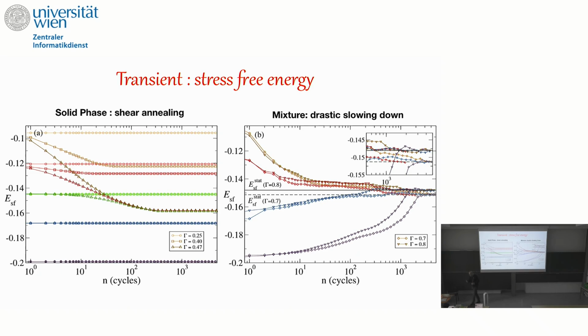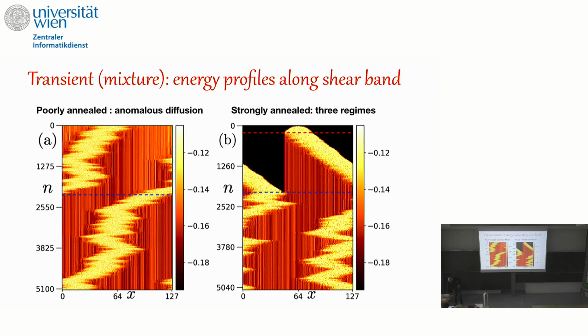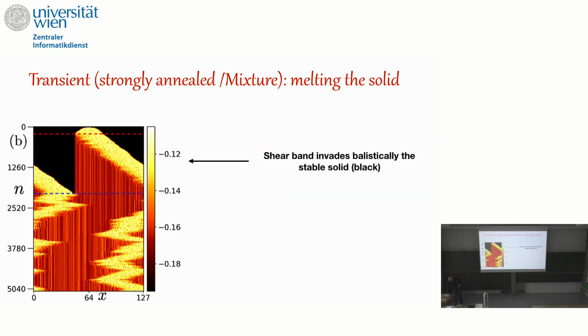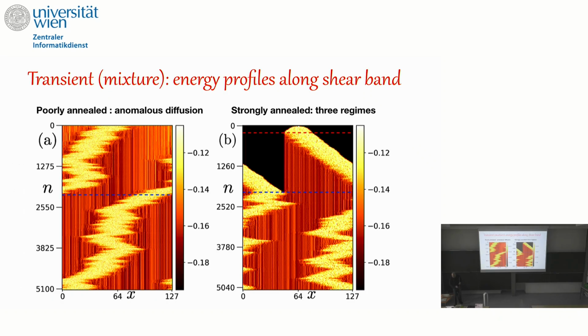And this is actually interesting, and I'm not sure that Shrikant agrees with me, because maybe I show directly. So let me show fast. If you are in the poorly annealed case, this is the number of oscillations, and this is the position of the shear band. What the shear band does is start to diffuse inside the sample, okay? And then you wait for it to diffuse in the full sample, which takes a certain time.